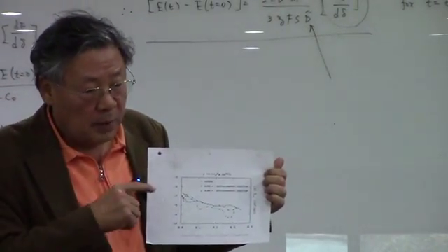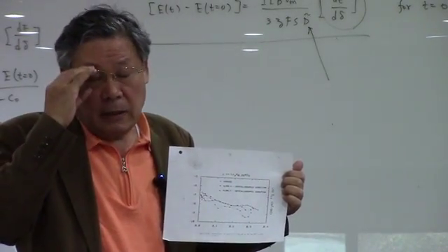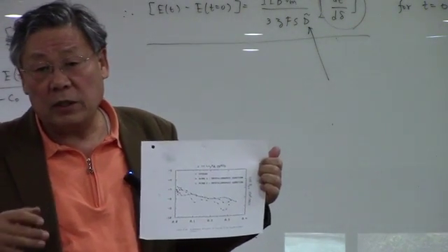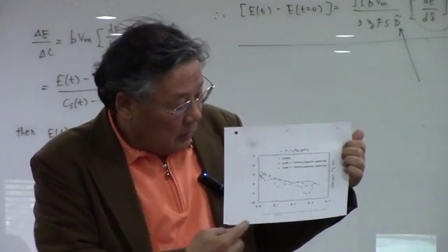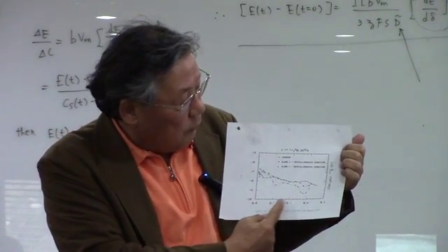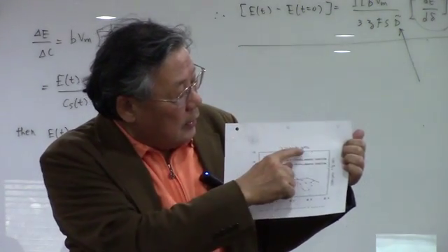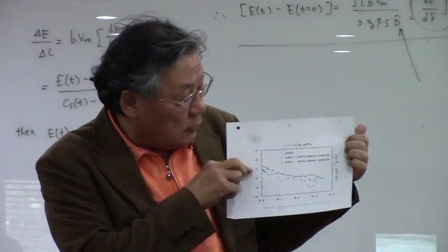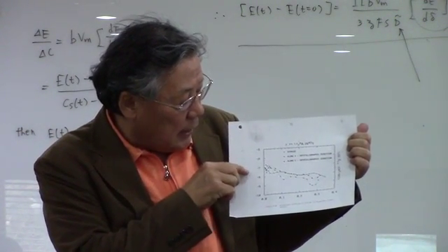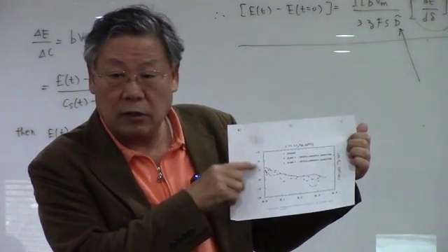Now, in normal practice, in Fick's second law, we just assume that diffusion coefficient is not changing with the concentration of lithium in the hexatungstate. But it turned out that as you move from here to here, this is Y in LiY, and the potassium hexatungstate here, the diffusion coefficient is changing from 10 to minus 8 to 10 to minus 9, 10 to minus 6 and 10 to minus 9 here.